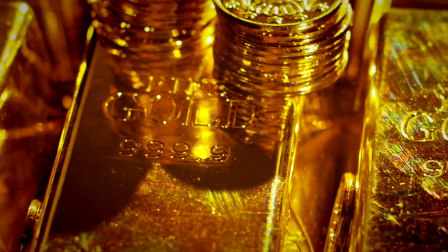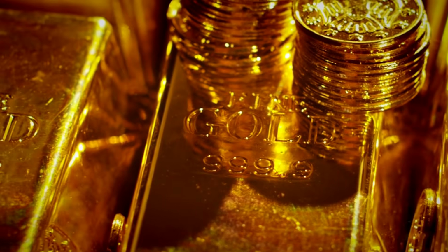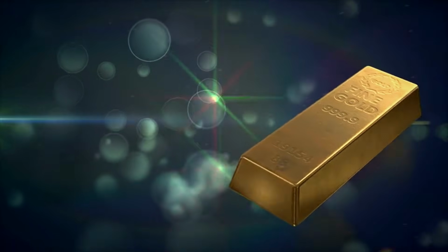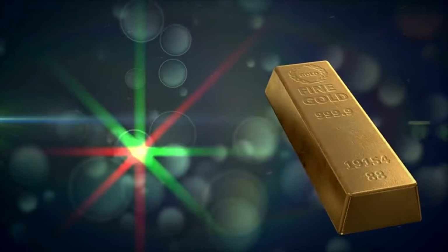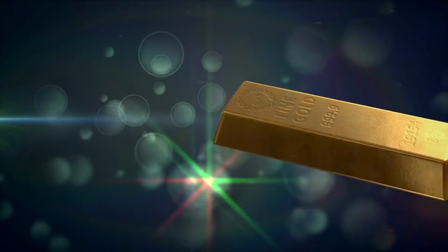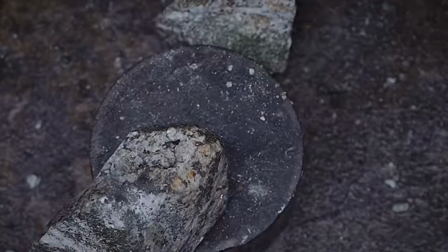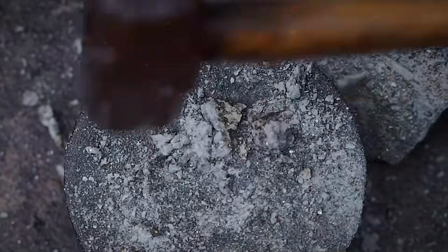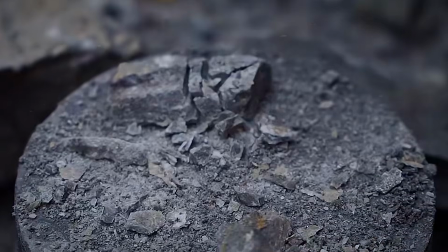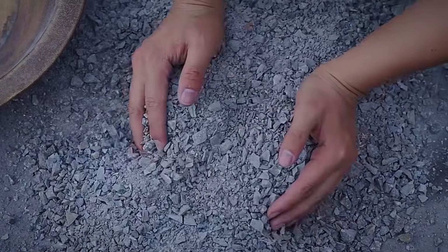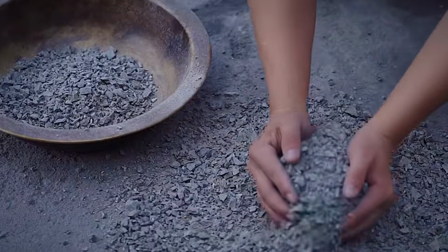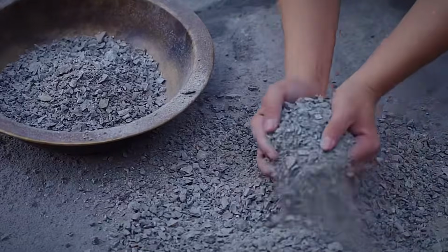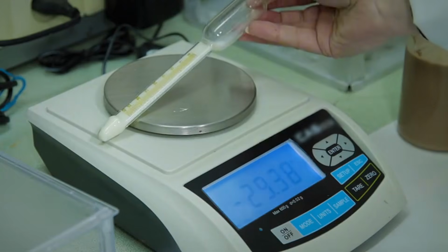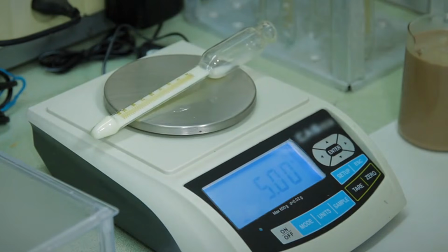It's a quick geological fingerprint. But false positives remain. One of the most common field misreads is mistaking mica for gold due to its shimmering flakes, especially when light strikes at low angles. Mica is soft, hardness 2.5, flakes easily, and appears in muscovite, silver, or biotite, bronze-black forms. Unlike gold, it floats, splits under pressure, and burns off under high heat.